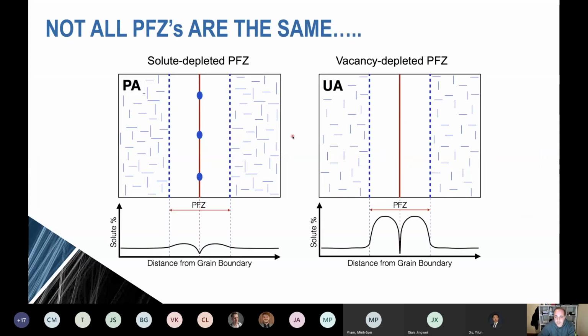Now, precipitate-free zones, in fact, are not all the same. They don't have precipitates, but the reason for not having precipitates comes in multiple flavors. In fact, when we first start aging a material, let's say for a short amount of time, precipitate-free zones are there almost as soon as precipitation starts. But initially, the reason that they are depleted is because they are vacancy depleted. The excess vacancies annihilate at the grain boundaries, and in these regions then there are not enough vacancies to have enough mass transfer to make the precipitates.